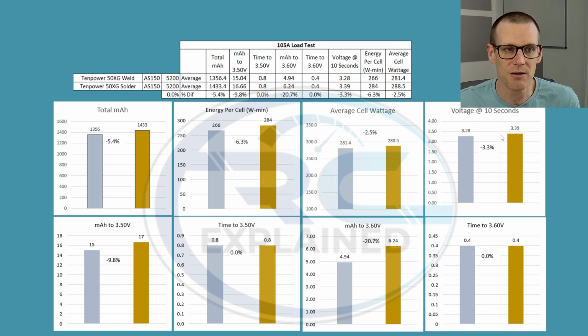Voltage at that 10-second mark. This was interesting to see: 3.39 volts on our soldered pack, but 3.28 volts, which is technically under that voltage cutoff that we typically use. So at the 10-second mark, that voltage cutoff would have tripped on our welded pack. The reason is that on our typical test for a lithium polymer pack, we have a voltage cutoff threshold and a temperature threshold. In this case, we ignored the voltage cutoff threshold and only went by temperature in order to compare the data between both of these configurations.